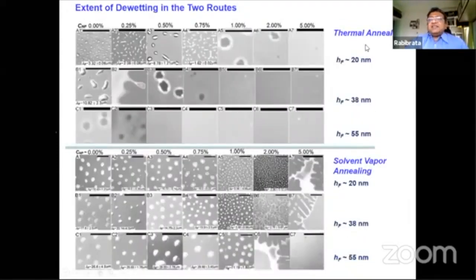And we can also see that in thermal annealing, these are the effects of the film thickness. So 55 nanometer, if you do a thermal annealing, it almost does not dewet. And 55 nanometer, if you do a solvent vapor annealing, it dewets pretty well. So again, the statement that addition of nanoparticles stabilizes a film needs to be relooked. It's a question of what triggering mechanism or dewetting engendering mechanism you are adopting that also needs to be considered. So if you say that, well, all films above 40 nanometer are stable if the nanoparticle concentration is just 0.05%, it also needs to come with a tag that if you do a thermal annealing, the same film is going to be unstable if you do a solvent vapor annealing. So these are very important findings that came out from this paper.